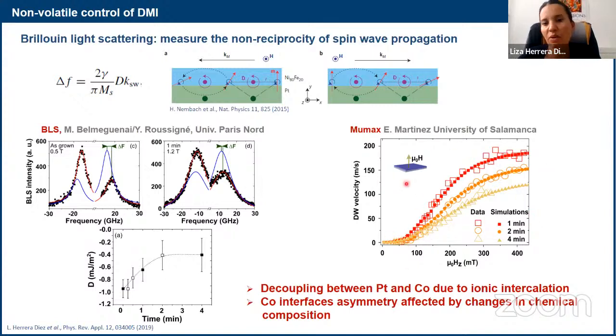Then also together with our friends in Salamanca, they did some measurements, and then they did some magnetic simulations, and it was really the changes that we're seeing with gating that were corresponding to variations in DMI and also in anisotropy, but in particular in DMI.